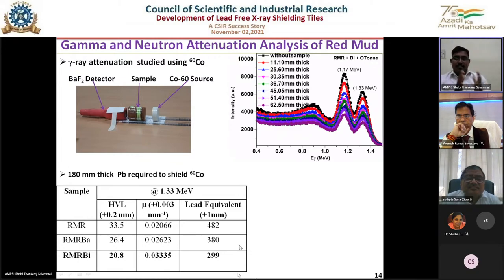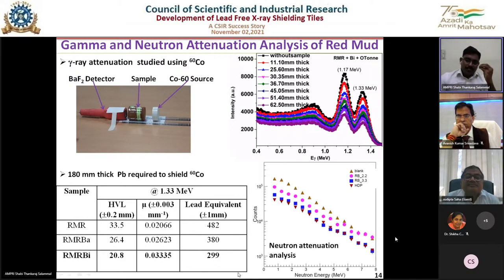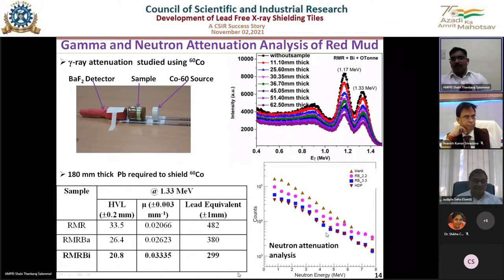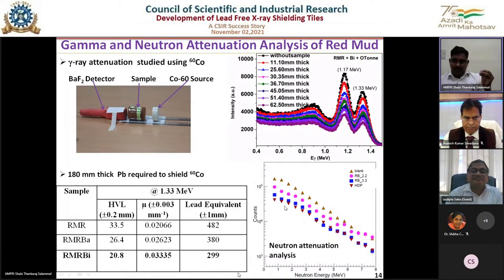Wherever they use lead, lead is structurally very weak, so they also make other concrete structure to give proper strength to the building. If we calculate the space also, our shield will consume less space because it has sufficient strength. Now if we see the neutron attenuation, here you can see the blank one. Normally for neutrons, high density polyethylene is suitable for shielding because of its large hydrogen content. The brown color corresponds to our sample, and it gives the same attenuation as high density polyethylene. So it is very good for both gamma ray as well as neutron shielding applications.